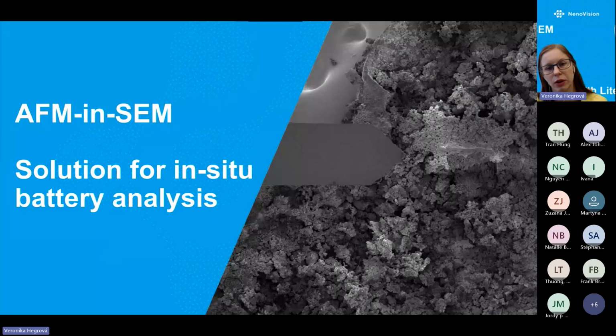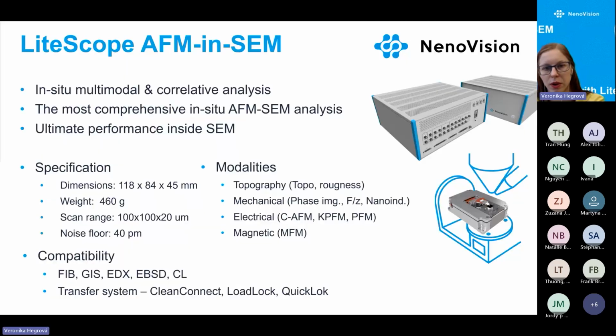So let's have a look at what solution we have developed for in situ battery analysis. First, we have LiteScope, which sits in the SEM stage with the control unit. From the modalities, what is quite useful for battery materials is topography, mechanical properties, and electrical properties, I would point out. It is compatible with much of what is already in the SEM, often focused ion beam, gas injection system, EDS, EBSD, cathodoluminescence, and we are compatible with Clean Connect, Load Lock, and Quick Lock from Thermo Fisher and Quorum.